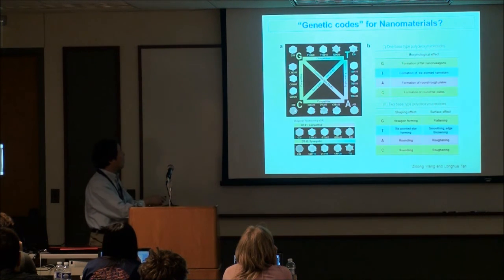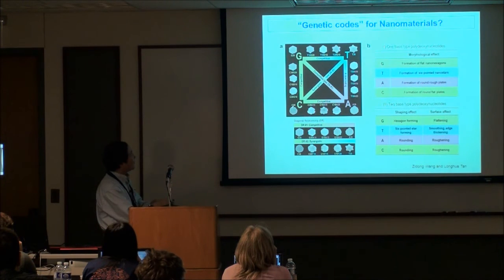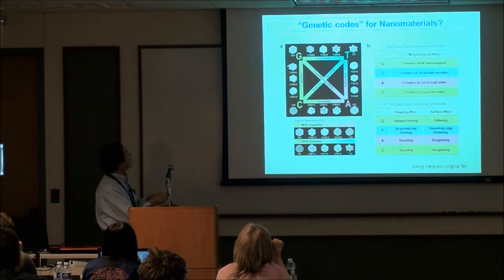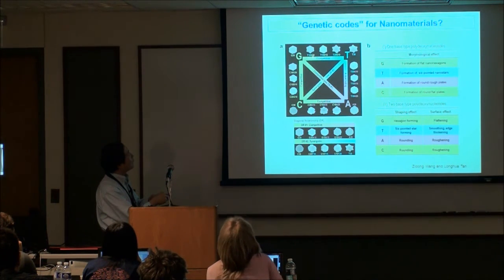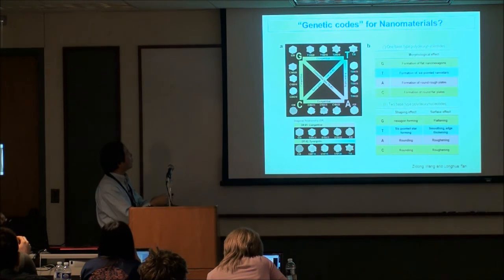So that's similar to what we showed here. But instead of completely whole sequences, when we start, for example, slowly increasing the T's from T10 to G20, T15 to G15, T20 to G30, you can see a slow migration from these hexagon shapes to these star shapes. And more importantly, you can go this way too.